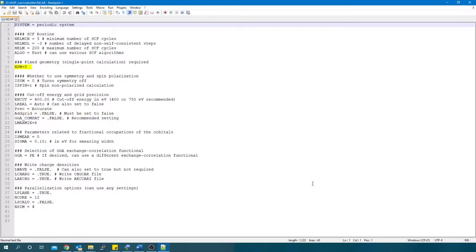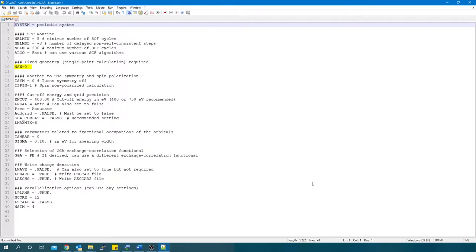NSW equals zero. No geometry changes. You can perform CHARGEMOL analysis on any kind of geometry you want, a DFT optimized geometry, an experimental geometry, a transition state geometry, or a non-equilibrium geometry. If you want to use an optimized geometry, you must do the geometry optimization in a separate prior VASP calculation before the VASP calculation to generate the electron density files. After you have the desired geometry, then run a VASP fixed geometry calculation with NSW equals zero to generate the electron density files for CHARGEMOL input.